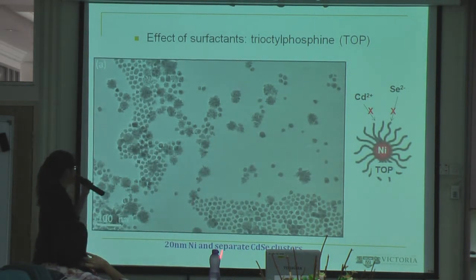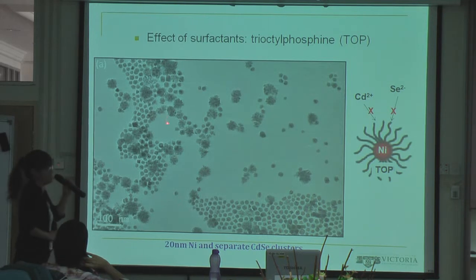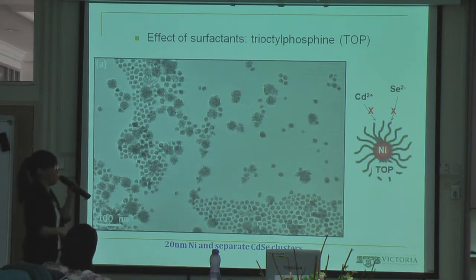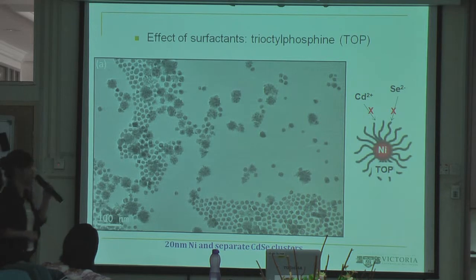What happens is that the cadmium selenide actually does not coat the nickel, it just forms separate clusters. This is because in the reaction mixture, if you remember previously when I discussed the preparation of nickel, to prepare the 20 nanometer nickel, I need to use the surface capping agent, which is trioctylphosphine. Trioctylphosphine binds strongly to the surface of nickel. At the same time, it also blocks the excess cadmium and selenium. That's why cadmium selenide cannot form on the surface of nickel. On the other hand, it only forms separate clusters. So how to overcome this problem?